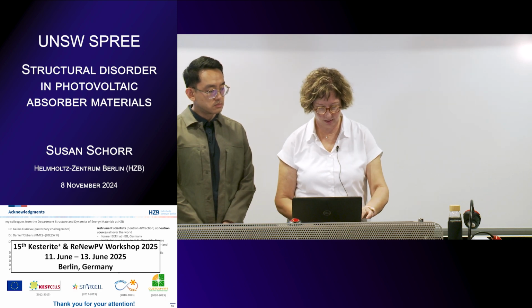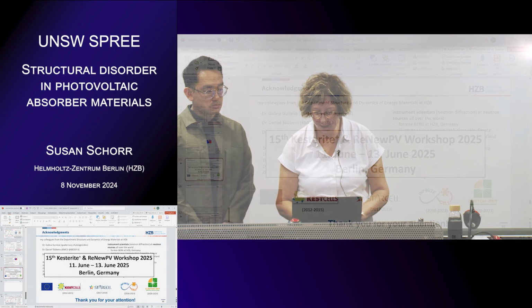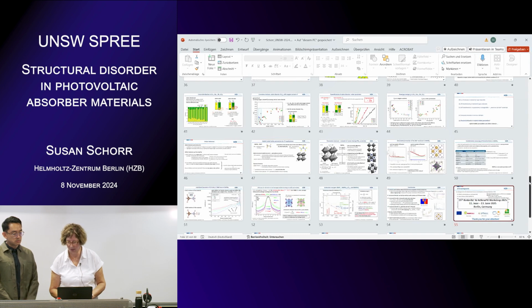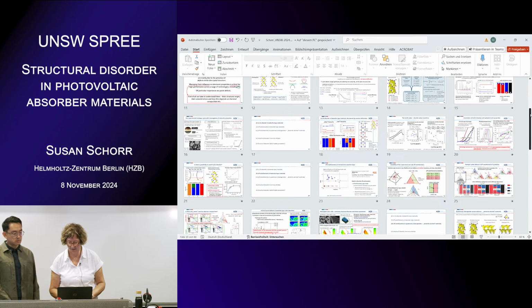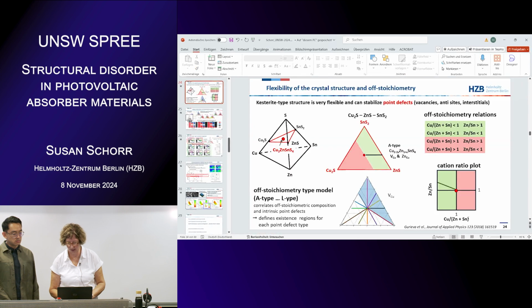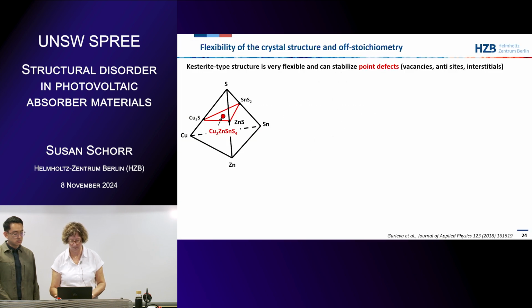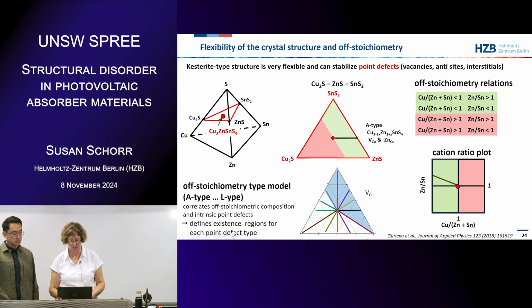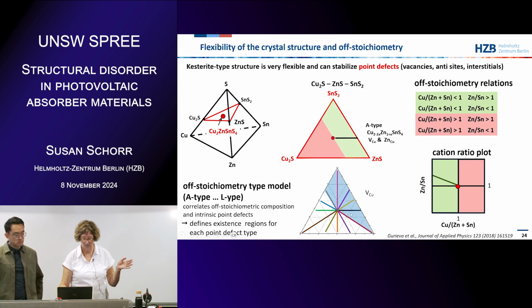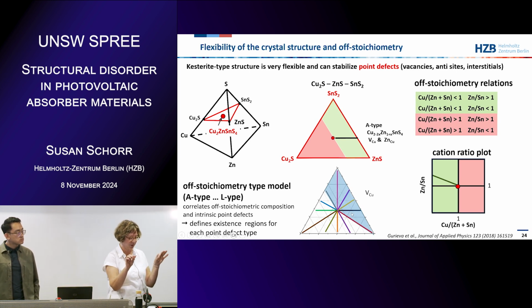And I will show it. I will go back to my cation ratio plot to show you that one. No, the final one. So, for instance, especially if you cross a line, if you cross one of these lines, then your composition will be not so different, but your stoichiometry type will be totally different. So you will have very different defects.